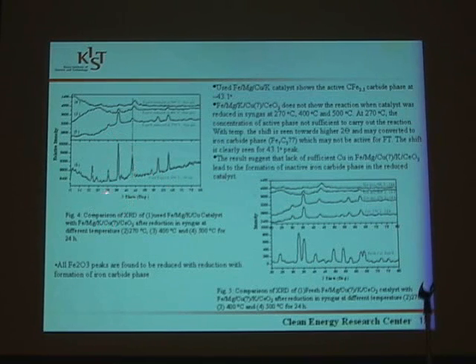This is the XRD figure. It shows the comparison of the XRD of the used precipitated iron catalyst and the magnesium promoted precipitated iron catalyst with the FeMgCu catalyst after reduction in syngas at different temperatures. So this catalyst is the spent catalyst after the FT reaction, and this is the first catalyst which we prepared here.